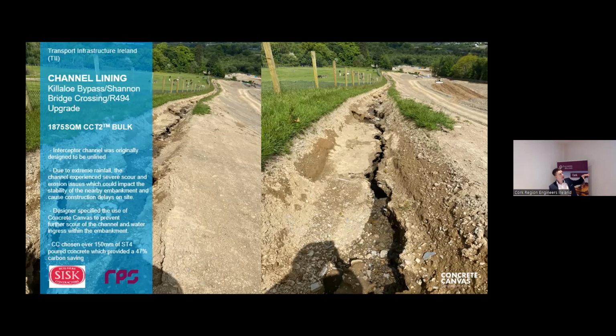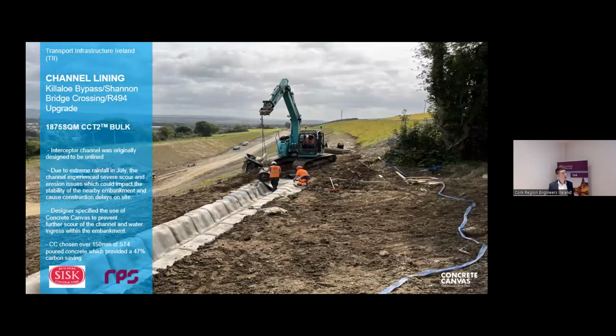And you can see, from that very dry weather to very wet weather, the amount of scour and erosion within the invert of that interceptor channel. And the risk here is the stability of the slope on the right-hand side because of that water ingress. If there's any issues there in terms of slippage, then you're going to have construction delays on site. So it was decided that it required a hard armor lining solution, and they required material quickly on site.